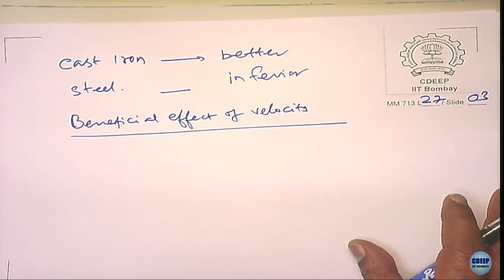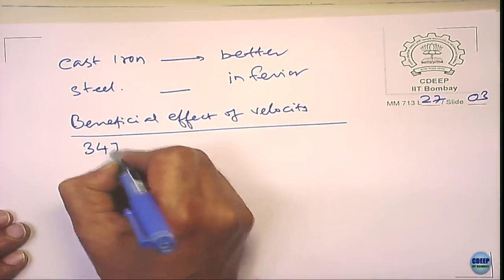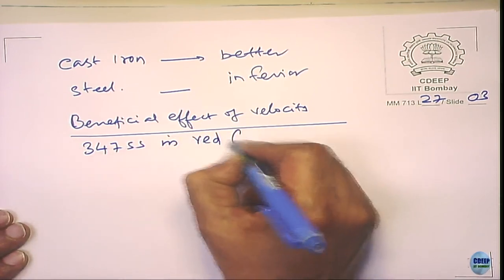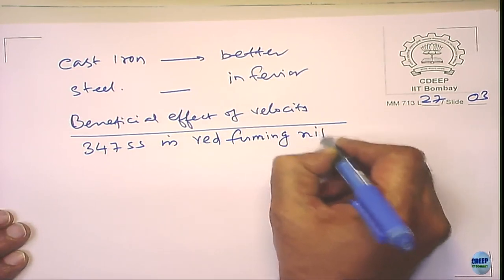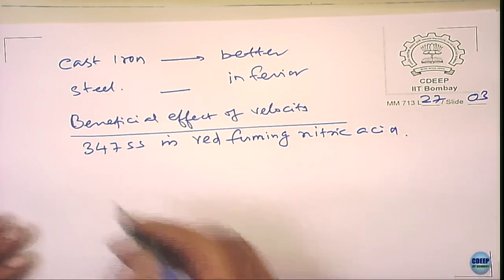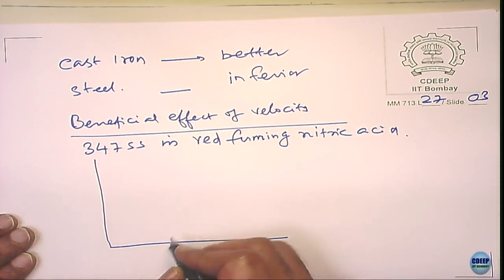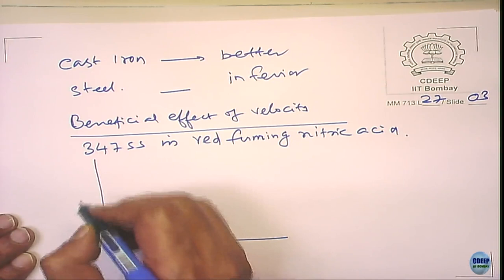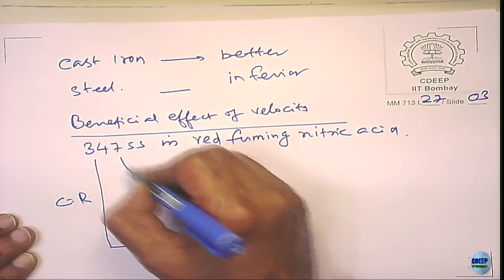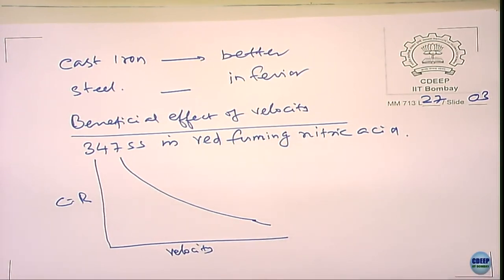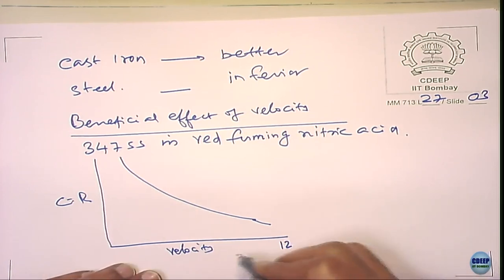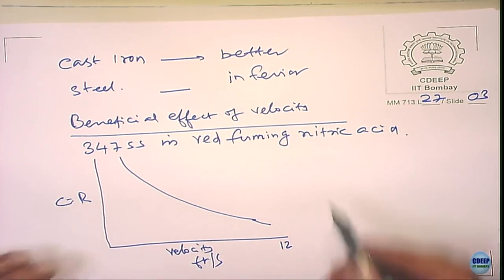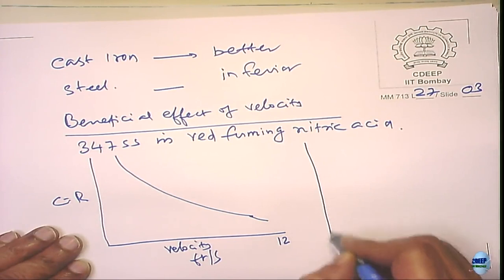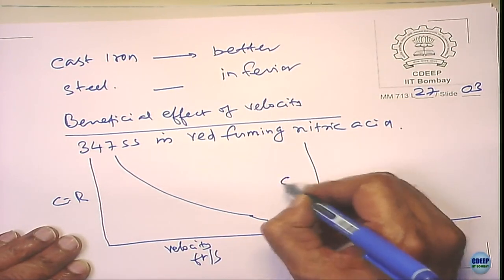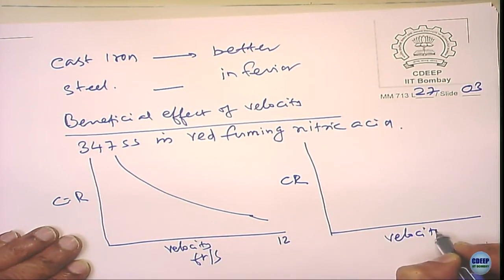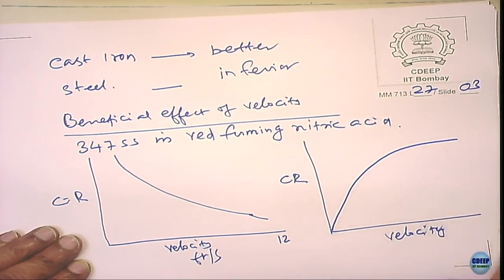This they have reported for 347 stainless steels in red fuming nitric acid. They found the corrosion rate drops like this, maybe within about, let us say, 12 feet per second, it drops like this. In the case of aluminum alloy, it is slightly different. Corrosion rate versus velocity, something like this.